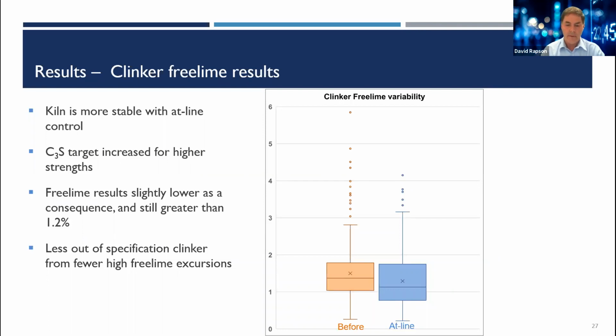So again, I've paired the freelime data here in the box and whisker plot. And the at-line data in the blue shows fewer outlier points above the graph, which means there's been less off-spec material going into the clinker silo. The average freelime is slightly lower, now at 1.2%, but the kiln's operating at a higher C3S target. So the plant's been able to improve its kiln stability with increased C3S to give them better early strengths, only reducing the freelime a small amount.